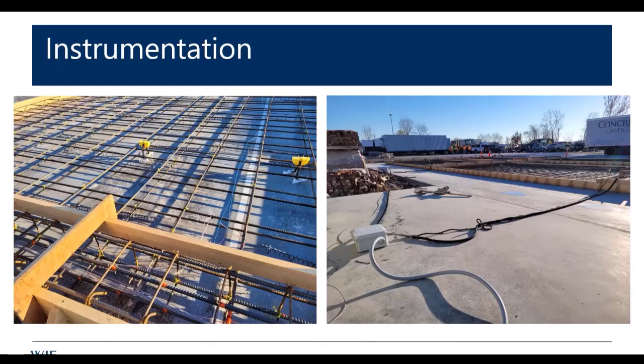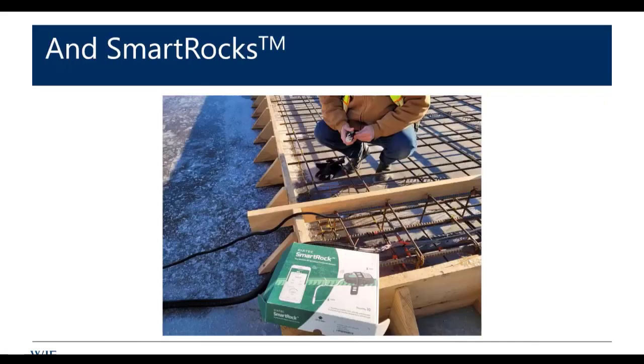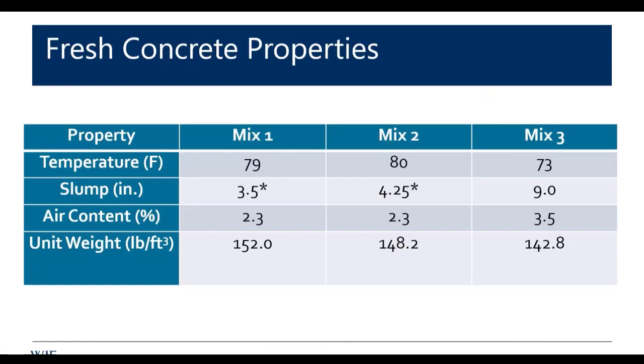We had strain gauging to measure strain and tilt and temperature, and the idea was as we tilted and rotated the panels, we'd get the strains. Of course, I think a bunch of our instrumentation cables got torn out, which was most unfortunate. So we didn't really get the strain gauging data that we were hoping to get. We also put a bunch of smart rocks in there for maturity, and so we had maturity curves developed, and so we had it completely metered there.